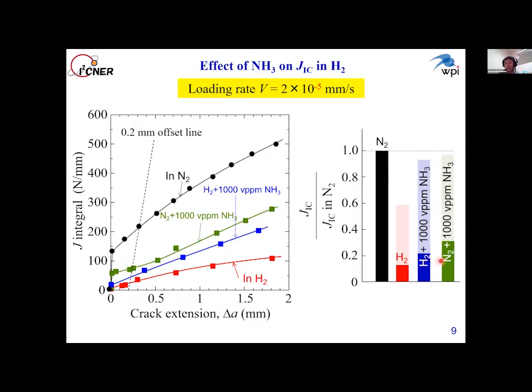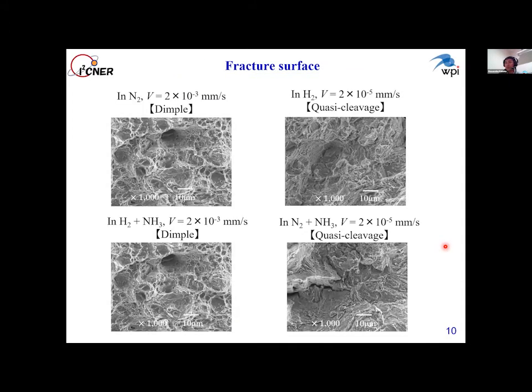What is most interesting in this experiment is the result obtained in nitrogen plus ammonia environment. The J1C fracture toughness value was significantly reduced, while ammonia had no effect in the previous experiment. So to clarify the mechanism of these results, we observed the fracture surface.